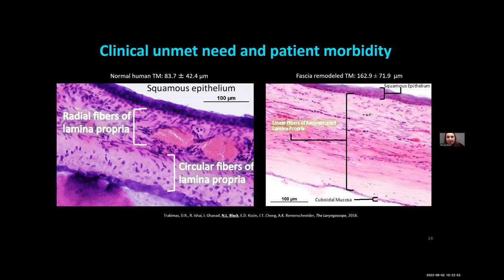However, if you take an eardrum that has been replaced with something like fascia and look at that under a similar histological section, you can see, for example, this graft is quite a bit thicker. It's about 160 microns. And additionally, it doesn't have this bilaminar structure to it. It really has just a linear sequence of these original fibers that were present in the fascia itself. So again, this is showing that pretty much whatever piece of autologous tissue you're going to put in, it's going to keep that same structure and it's not going to remodel into the native architecture.